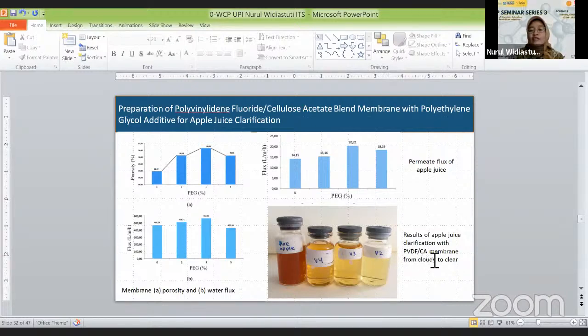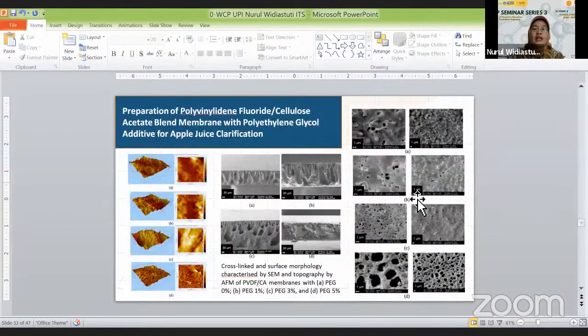And as we can see, the result of the apple juice clarification with PVDF and cellulose acetate membranes goes from cloudy to clear here. And this is the permeate flux of the apple juice. And this is the characterization of the membranes, the cross-section and surface morphology using SEM and also the topography by AFM of the PVDF-CA membranes with polyethylene glycol at various concentrations. And we can see here the effect of polyethylene glycol at the lower concentrations.